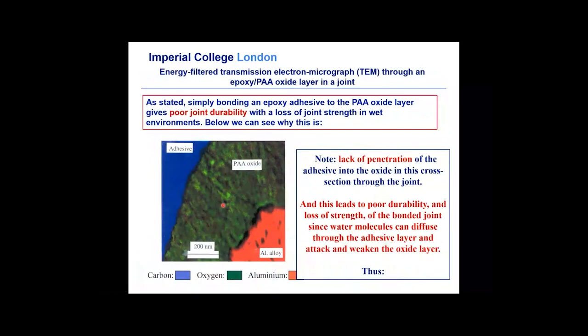What we found in the research we were asked to undertake was that if you applied just the epoxy adhesive straight to the oxide, you actually got poor joint durability. And we wondered why. The reason is here; this is a section again, so we're looking sideways on. This is an energy filtered TEM, and energy filtered TEMs allow you to identify elements. So we have the adhesive here, which obviously goes off the slide into the distance. Here's about half a micron, 500 nanometers, of the oxide generated by phosphoric acid anodizing. Here's the aluminium alloy.